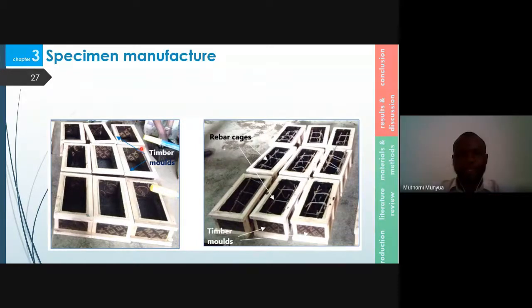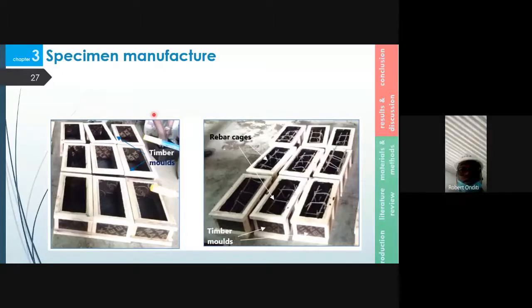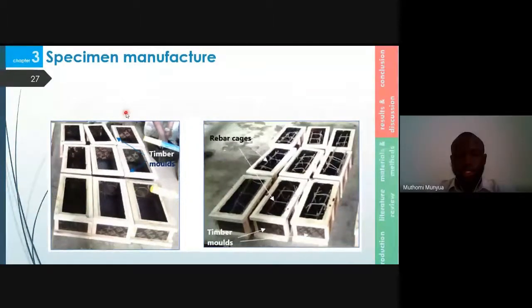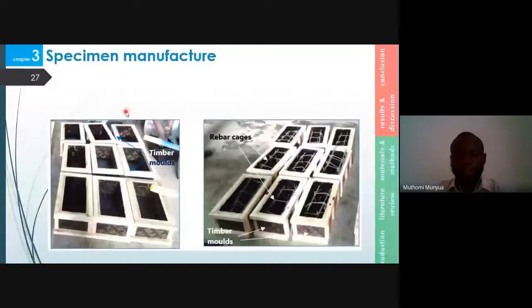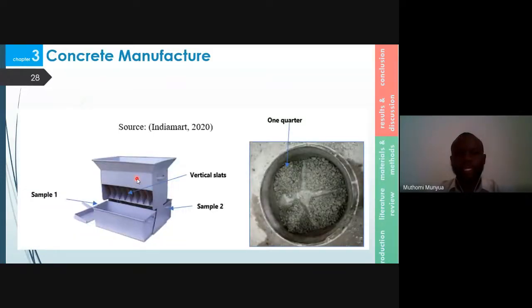I'll continue. So therefore, the molds were made of marine ply, and engine oil was used as the shutter release agent. You can see elements with rebar and those without. Quality control measures were employed throughout the study. In this case, we did riffling and quartering while batching the concrete.